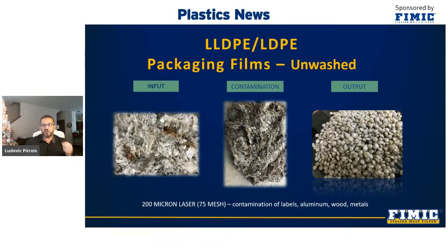In this example of unwashed polyethylene film from packaging, we use a laser quality screen with perforation of 200 micron, an equivalent of 75 mesh in woven meshes. These pellets are reused among others to make blown film of 20 micron thick, such as garbage bags. The average of our discharge consists of 99% contaminants and only 1% useful plastic. So our discharge is among the lowest between the different filtration systems.